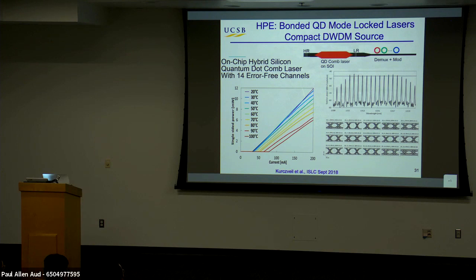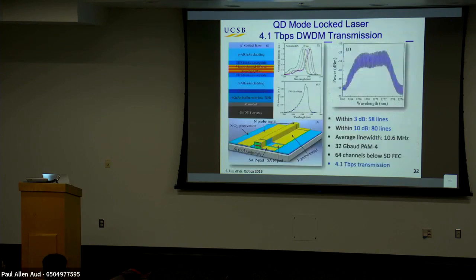So that's one example. You can go even further, and this is some work we've done at UCSB. In this case, we're not making uniform quantum dots, we're intentionally chirping the quantum dots. The reason we're chirping them is we're trying to get a broad gain region, broader than you'd get naturally from quantum dots. This shows the spectrum of layers of quantum dots in there. As we change the growth characteristics, we can change the different layers to have peaks at different wavelengths. And that gives us overall a wider gain spectrum. So now, rather than trying to get down to 20 meV or 10 meV, we're now broadening it to 70 meV.